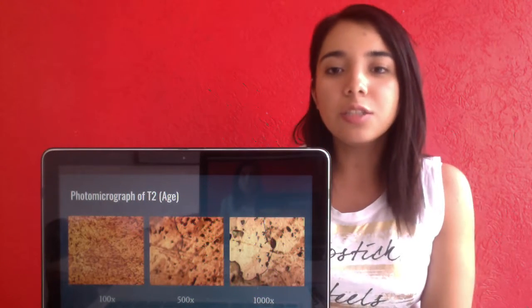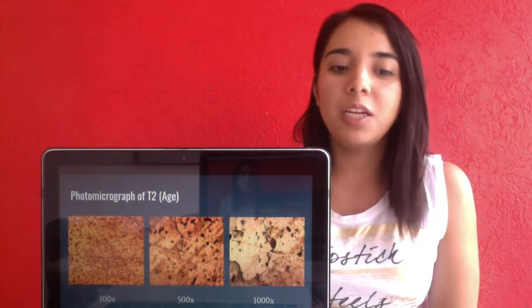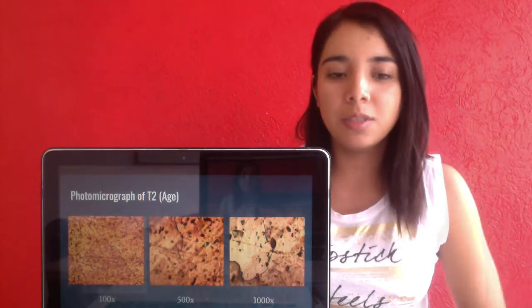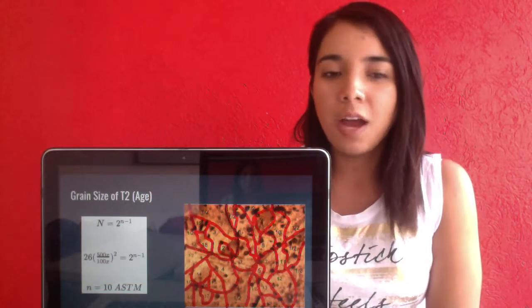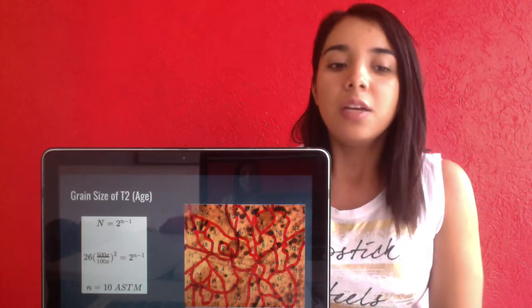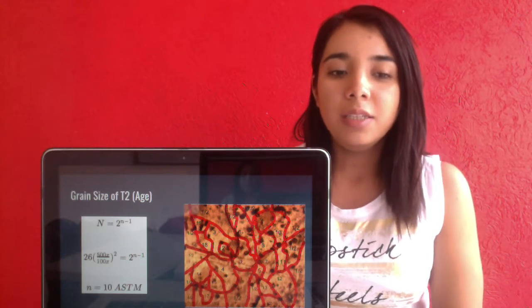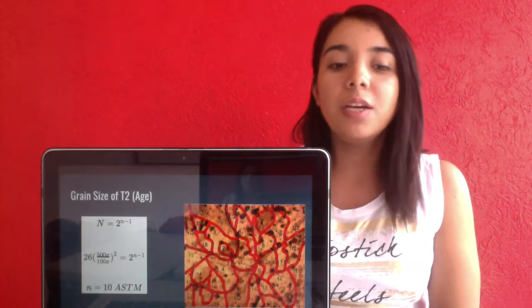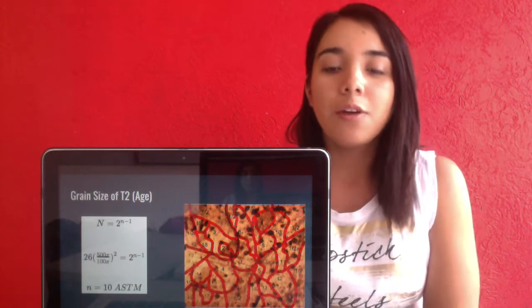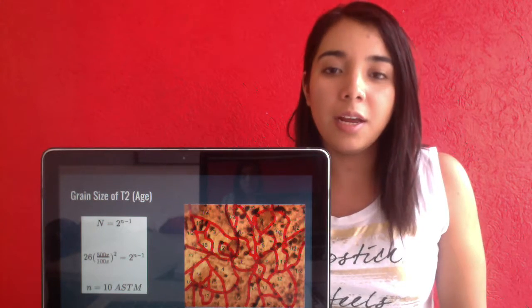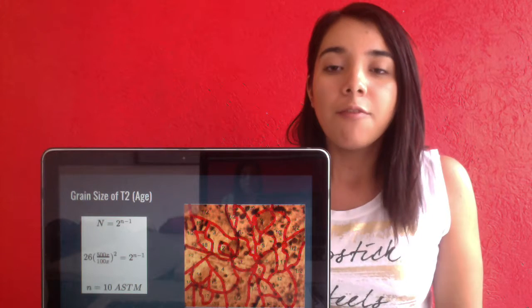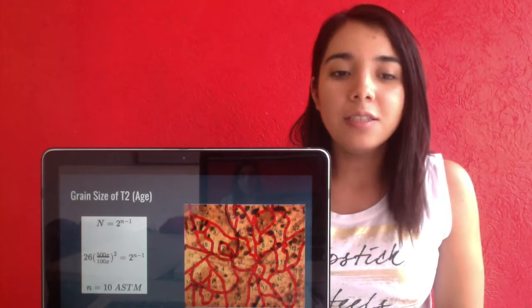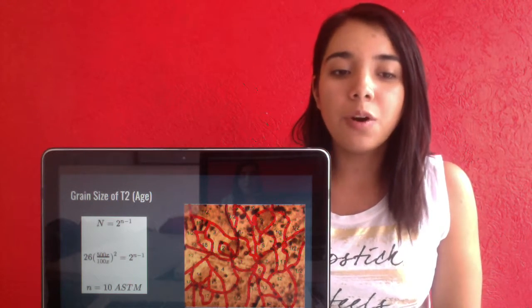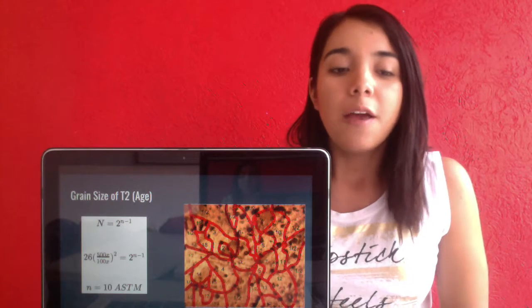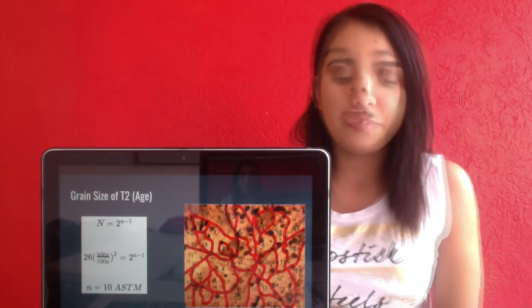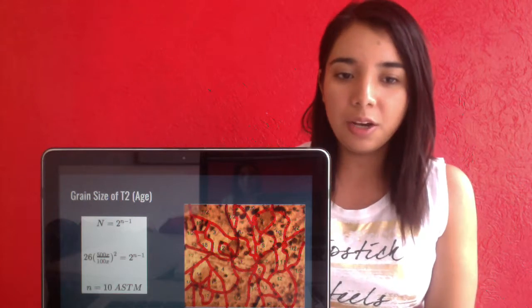For the second heat treatment, we use the same magnifications, 100, 500, and 1000. At the magnification of 500, we saw 26 grains, and we adapt the formula. We obtain an ASTM of 10, that is a greater ASTM than the first heat treatment. In this, we saw more grains. Then this has better mechanical properties than the others.